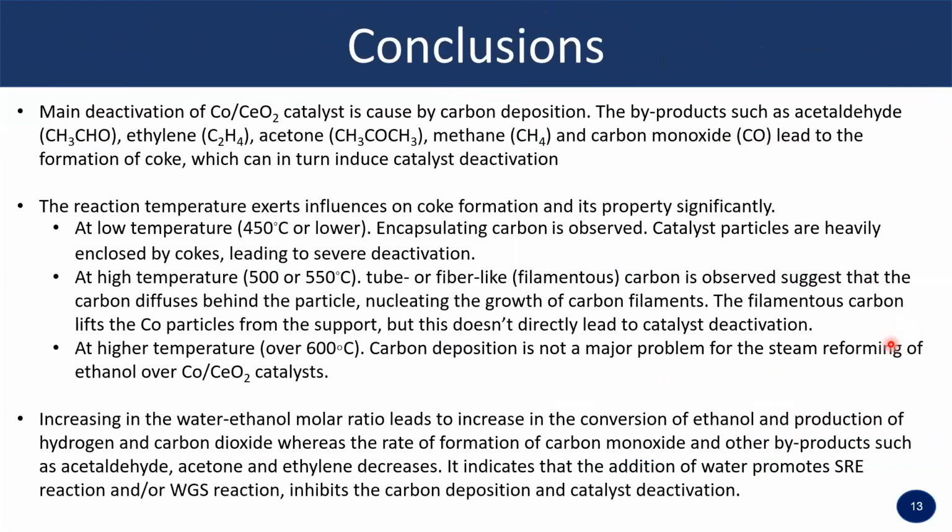And for conclusion, the main deactivation of Co/CeO2 catalyst is caused by carbon deposition. The byproducts of ethanol steam reforming lead to the formation of coke, which can in turn induce catalyst deactivation. And the reaction temperature exerts significant influence on coke formation and its properties. At last, a higher water ethanol molar ratio is one possible strategy to reduce the carbon deposit.